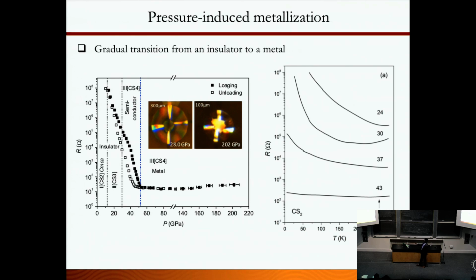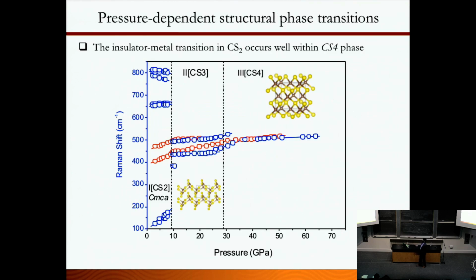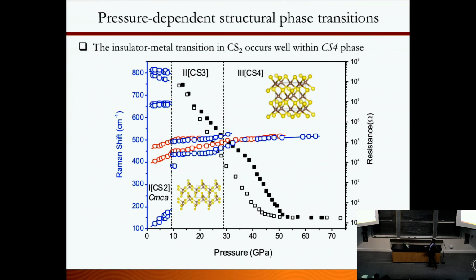Low temperature resistance studies also show that it's going through an insulator-metal transition. If I put all these phase transitions on top of the resistance measurements, it nicely matches the new phase that we were observing right here, the new CS4 phase, the fourfold coordinated carbon disulfide phase. The insulator-metal transition is well within phase 4 of the carbon disulfide.